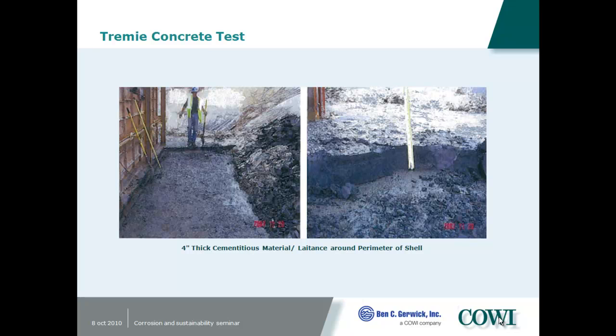So this shows some of the overflow. Inside of the shell, we required the contractor to put in more Tremie concrete than the volume required, so some of the laitance would flow out the top. And in this test, after it flowed out, it wasn't contained and it mixed with the water, so there was more laitance there than what was really the case in the river. And in the river, it flows into the legs of the lifting frame so that it doesn't mix with the water and affect the environment.